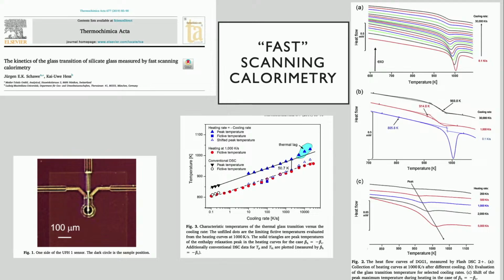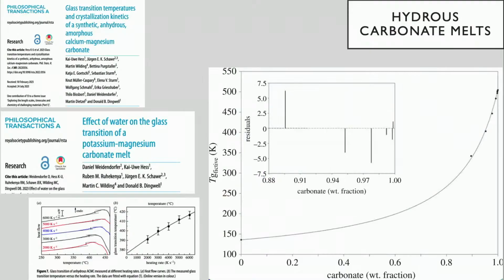The latest kind of calorimetry applied to all of this is a new kind of calorimetry. It's called flash calorimetry. It employs heating and cooling rates of thousands to 10,000s of degrees per second. Now you say to yourself, surely, how in the world can they heat something with 1,000 degrees per second or 10,000 degrees per second? It's done by applying power to a chip, to a microchip upon which the sample sits, and the sample is extremely small. And the heat transfer is extremely efficient. And with those kind of heating and cooling rates, we can manipulate samples that would normally never form a glass, but they will form a glass for the fraction of a second that is required to get these kind of data.